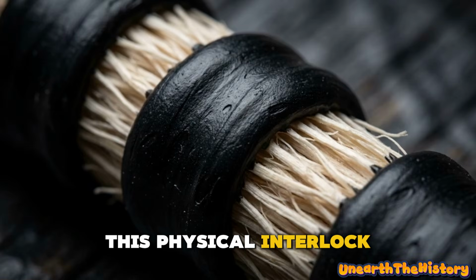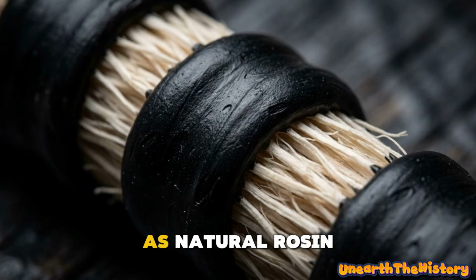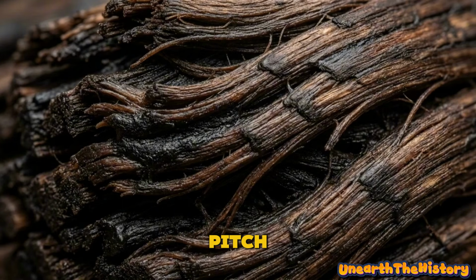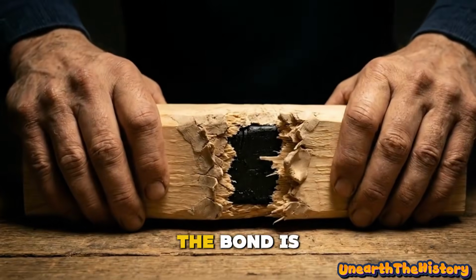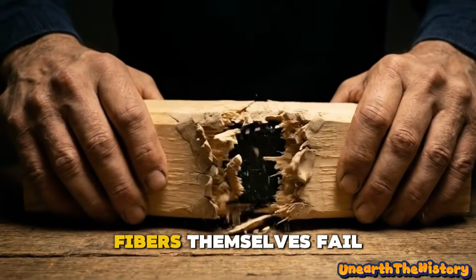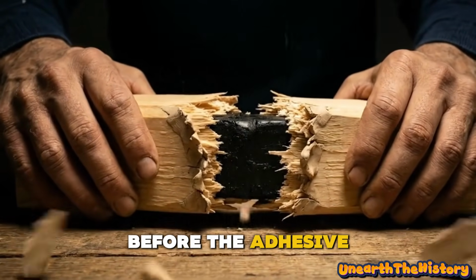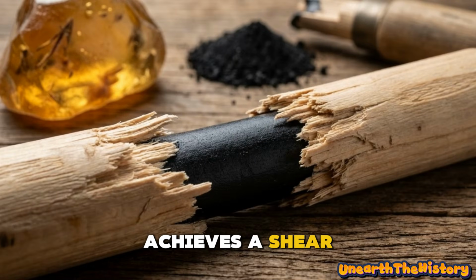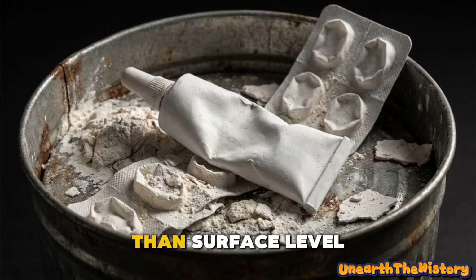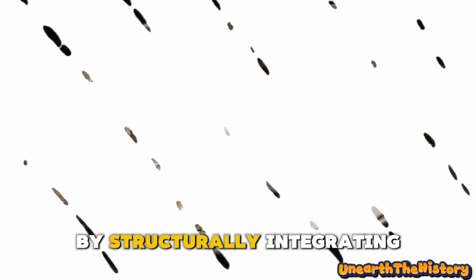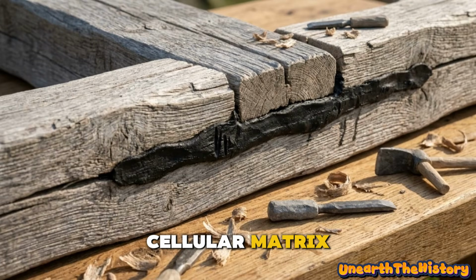This physical interlock is supplemented by a chemical bond, as natural rosin acids in the pitch grip the cellular fibers of the wood. During a destruction test, the bond is so integrated that the wood fibers themselves fail before the adhesive joint yields. This engineered biocomposite achieves a shear strength higher than the original wooden substrate. Ancient resin adhesives achieve higher strength than surface-level synthetics by structurally integrating into the wood's cellular matrix.